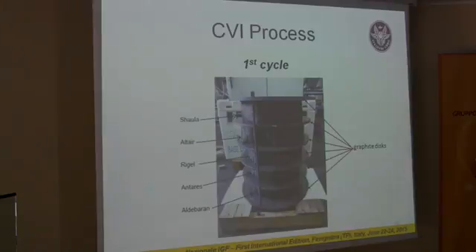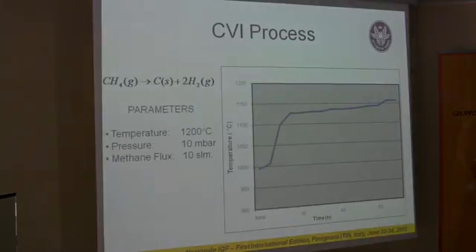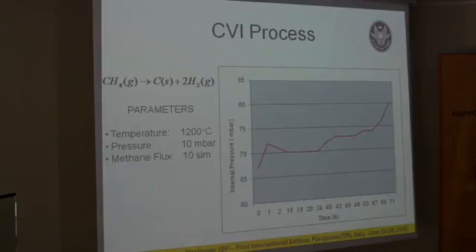The gas inlet is placed at the bottom, and the gas flows from the hollow core towards the external zone. The chemical vapor infiltration process is based on the decomposition of hydrocarbon molecules at high temperature that results in the precipitation of carbon atoms that are deposited and intercalated between the carbon fibers of the substrate. Thus, the temperature of the reaction, the operating pressure, and the flux rate of the hydrocarbon are the main parameters to be set up and controlled during the whole process in order to avoid sudden environmental change. That is important, particularly for the gradient of pressure between the hollow core and the external zone.